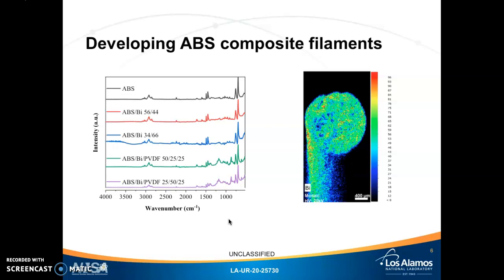Also note that the bottom two curves have all three components, and that a peak characteristic of PVDF around 1200 wave numbers, which corresponds to a carbon-fluorine bond, is only exhibited in the filaments with PVDF. The XRF image on the right shows a color mapping of elemental bismuth in a cross-section of a filament at an angle. Using these two techniques ensures that the polymer and metal fillers have been successfully incorporated into the ABS matrix.